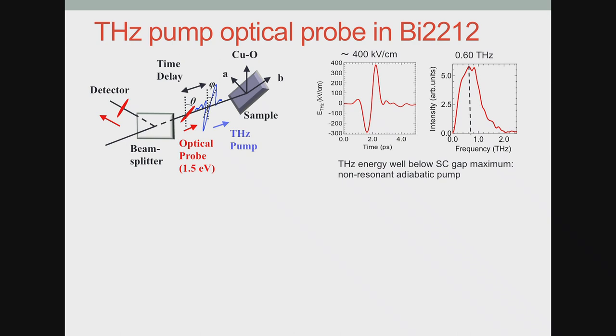So we are working on crystals. The setup that I showed you, where we were looking at the transmission measurements, was on thin films. Of course, on crystals, those are bulk materials, so you cannot really transmit your terahertz wave. So what we did is actually to use a setup where you pump with terahertz, but you look at your nonlinear response by probing its effect on the optical reflectivity, so a high-energy response.